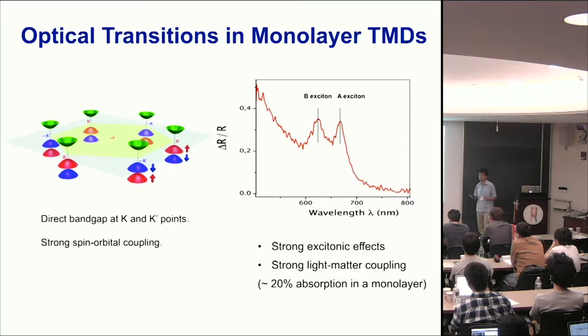It is known that for a monolayer transition metal dichalcogenide, when you shine light, you always generate an electron and hole together, and they form a tightly bound complex known as an exciton, with a binding energy of about 500 meV. That's much larger than in a typical semiconductor. Say, in silicon or gallium arsenide, the exciton binding energy is only a few meV to 10 meV.